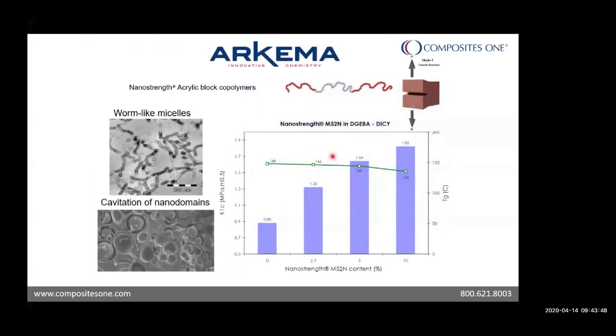The next one I want to talk about is the Arkema NanoStrength. This is a functionalized nano copolymer chain. It's got a polybutadiene center with polymethyl methacrylate ends that allows it to bond into epoxy. So this improves toughness as well. What I show here is K1C toughness. You can see here at 0% loading, we had a 0.88 K1C. And then if you move to different loadings, like for instance the 5% loading of the NanoStrength, we show an almost doubling of the K1C toughness.